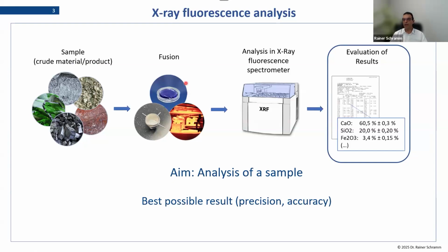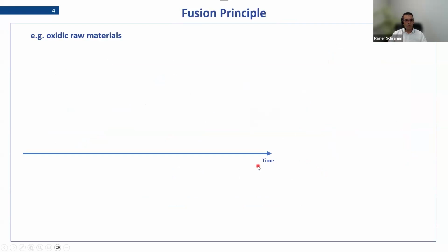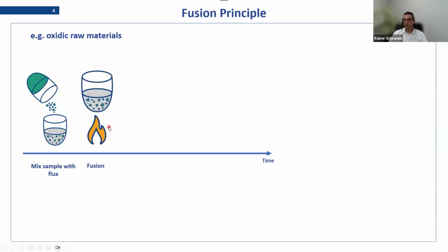And for every weighing step, there is the real question, how precise we have to weigh this to still get the best out of our XRF method. And this is what I would like to talk about today. So fusion, shortly, how does it work? We have our sample and we mix it with a flux. And mixing means really that you have it well homogenized before, so that you have the maximum contact between sample and flux, so that it dissolves as easily as possible when you put heat on it.